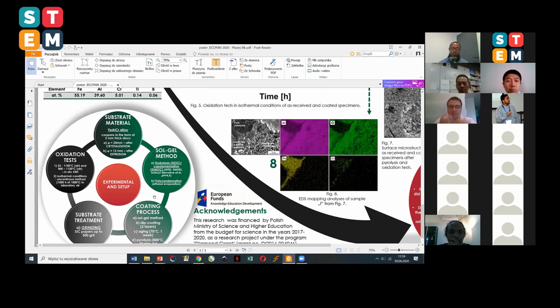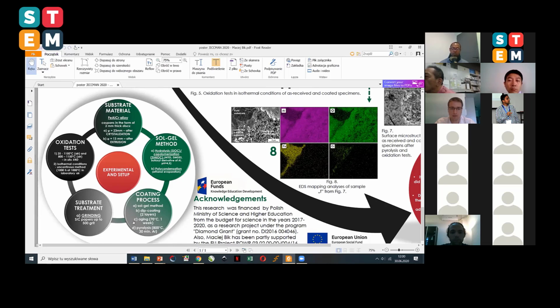So the first part of the study is the in situ XRD investigations, both in the high temperature range, so 800 to 1150, and also taking into account the lower temperature range, from room temperature to the same 1150. And in the second part, I applied coatings that I talked about a little, let's say, 1 hour ago, based on polymer derived ceramics. So just a quick reminder, I'm obtaining these coatings by means of the sol-gel method, so hydrolytic polycondensation, and after preparation of a sol, I'm using the dip coating technique to deposit very thin layers, and then I'm aging it in air atmosphere at 70 Celsius degrees for 1 week to let the solvent evaporate and polycondensation occur. And after that, I'm pyrolyzing my samples at 800 Celsius degrees for 30 minutes in argon atmosphere.